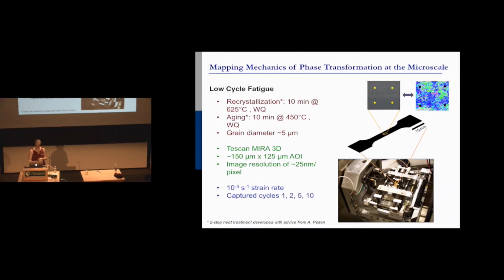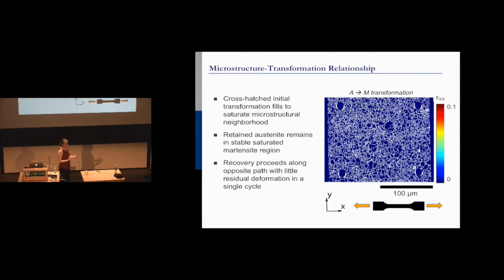EBSD. Okay. So when we use this approach and we look at, remember that big band we got when we pulled the material? You're going to see that band come through this field of view. This is 200 microns in width, and you can see all the grain boundaries in white. And you can see our little scouting markers right here from our FIB deposition. FIB is focused ion beam. It's like a really, really small mill. You can mill out. You can also deposit things in the SEM. We deposited platinum so that we would know where to find our field of view again.